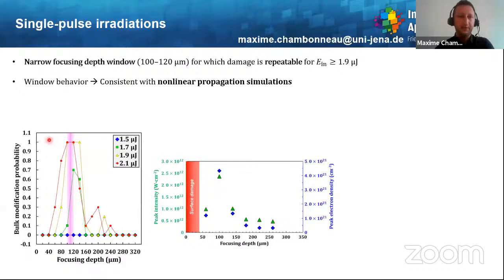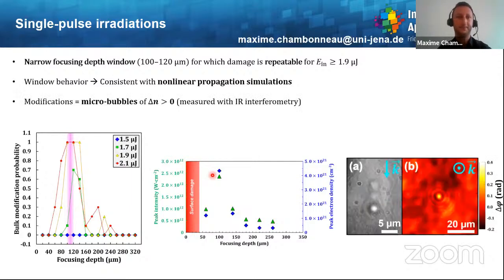So this window behavior shown here was extremely consistent with a nonlinear propagation model, which is developed by my colleagues that I will acknowledge at the end of my talk. And by performing those nonlinear propagation simulations, we were able to see that around 100 micron focusing depth, both the theoretical peak intensity as well as the peak electron density should be enhanced compared to other focusing depth.